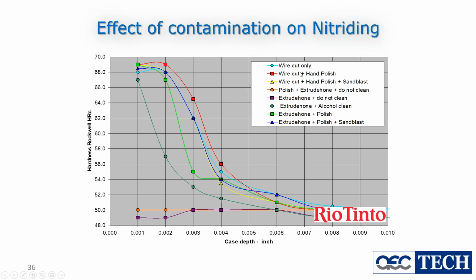All the ones that have got hand polishing on them go well. So a final hand polish is really quite important prior to going into the nitrider on the bearings. But please, polish is the key word here. Polish and clean. This is not grind away massive amounts of steel. So really, ANSI 600 or ISO 1000 paper, you're trying just to remove dirt. You do not want to move steel. But if you get it right, like wire cut and hand polish, which is how your die makers will deliver it to you with the first nitriding, you can see we get a fantastic curve compared to the ones with a greasy surface.